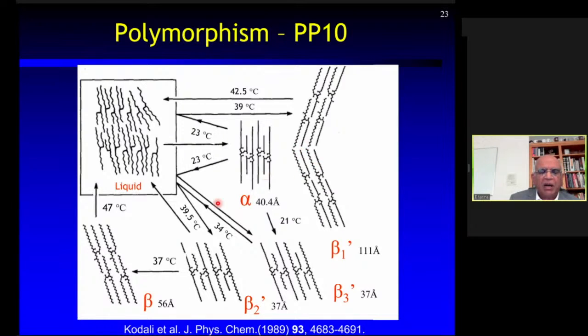And 3 of them are metastable structures, alpha, beta prime 2, and beta prime 3. And more stable structures are beta prime 1 and beta. And beta is the most stable. As you can see, in these 3 metastable structures, the short acyl chain C10 packs along with the longer acyl chain C16 chains, whereas in these 2 stable structures, that shorter chain segregates and forms a middle layer in between the 2 palmitoyl layers.